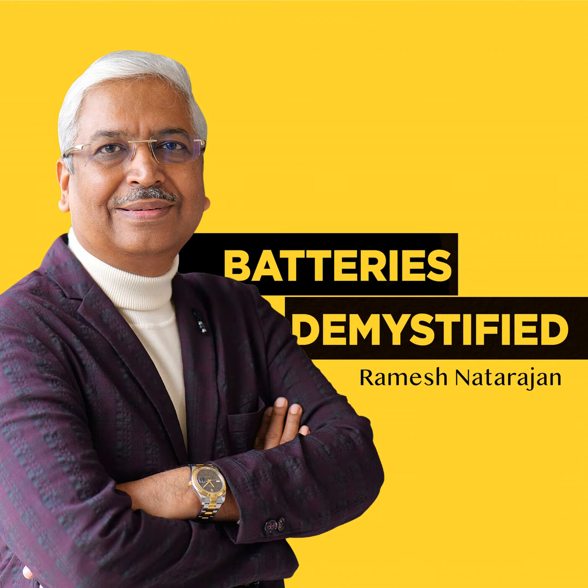To confirm that electrolyte starvation is the cause of this cell's failure in the capacity test, one should remove the group from the cell container, place it in a larger container, and thereby increase the volume of electrolyte. The capacity test performed with the same plate groups in a larger container with more electrolyte may solve the problem.